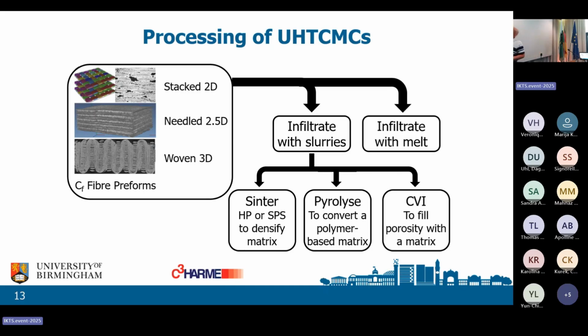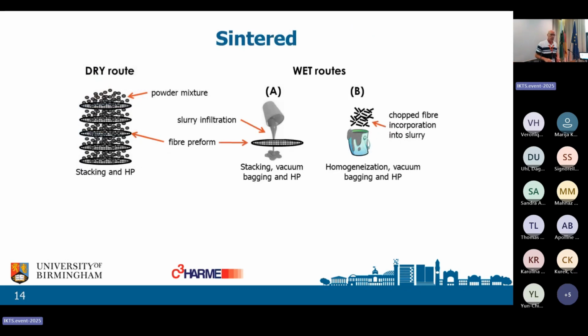But then you infiltrate with slurries, and then you sinter it, hot pressing, spark plasma sintering. You pyrolyze a monomer, the PIP process. You use CVI, or you don't infiltrate with a slurry, but you infiltrate from a molten metal. So sintering. The basic concept, you've got two alternatives again. You can use a dry route, you can use a wet route. You can also, of course, use chopped fibers. Now, chopped fibers don't give you the same performance, but they do improve the performance, so they are worth considering.